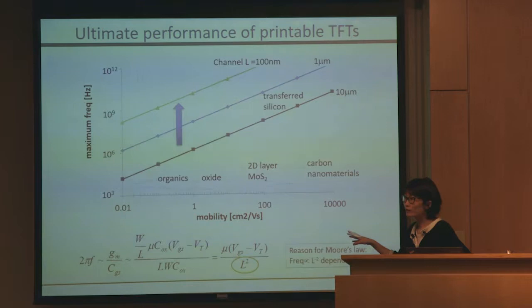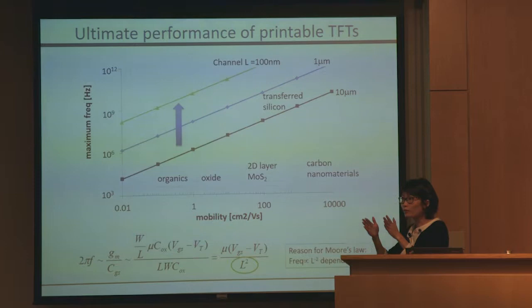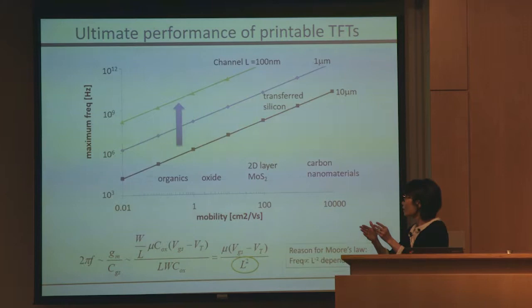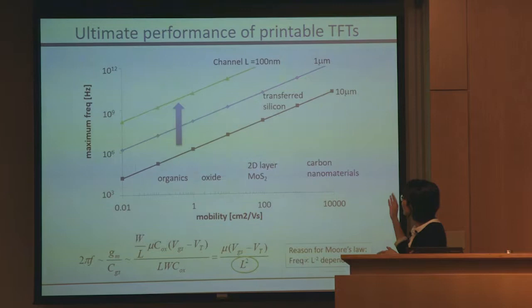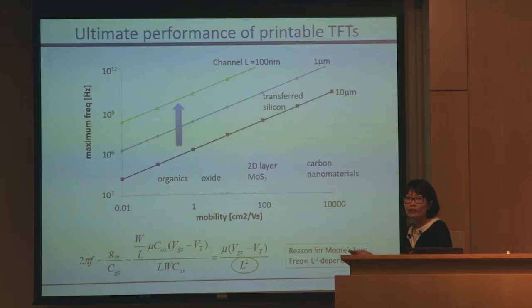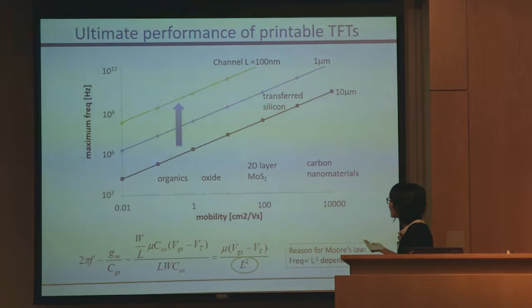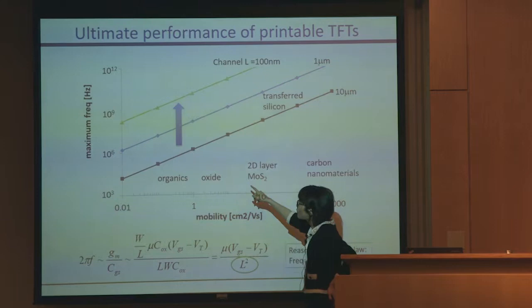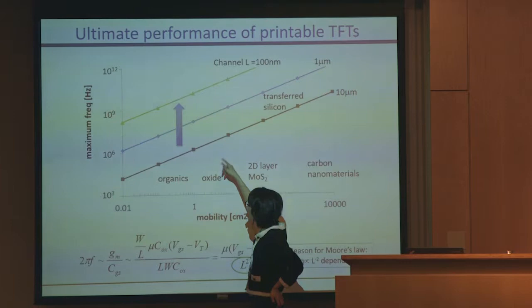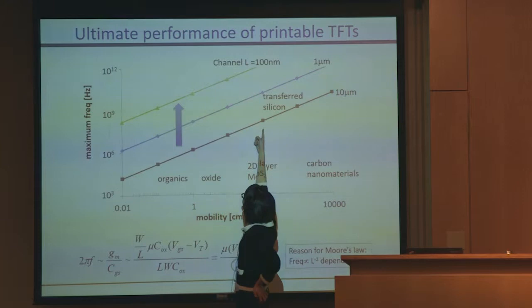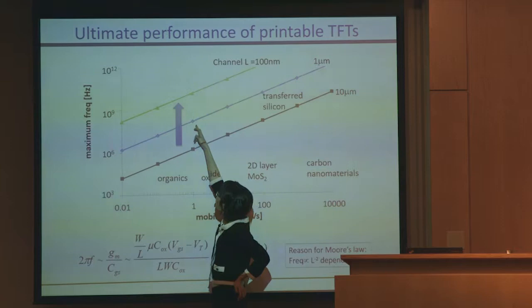And when you pattern a device, the electron has to move from one electrode to another, and the gap between that will also determine your transistor performance. And by changing that resolution, by changing that gap, you actually win a lot of performance without changing the material. For example, if we change the resolution of that gap from 10 micron to 1 micron, we win 100 times in terms of the maximum frequency. That's almost like changing your material to something very exotic and very high performance. So this is 100 times, and that's 100 times in mobility.